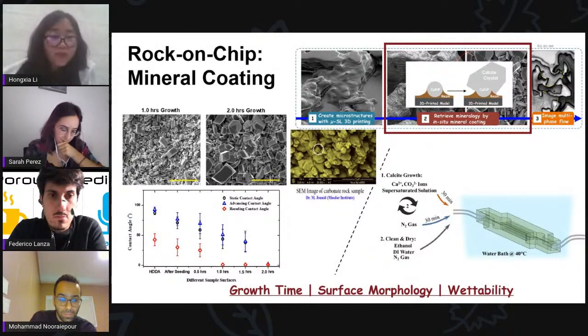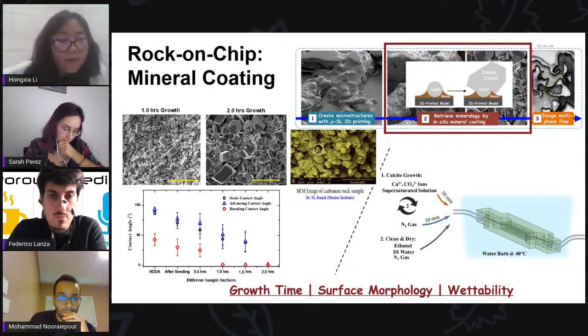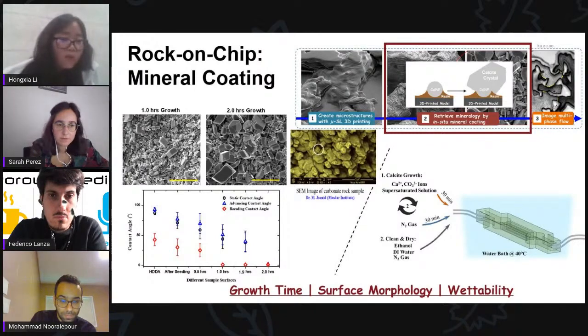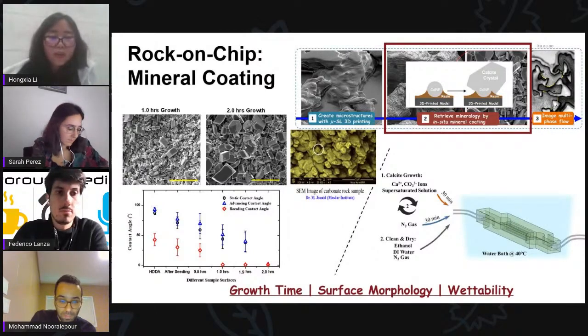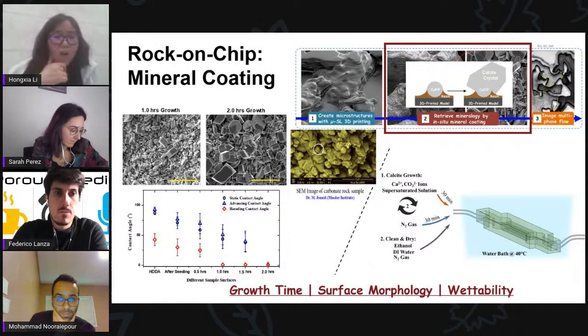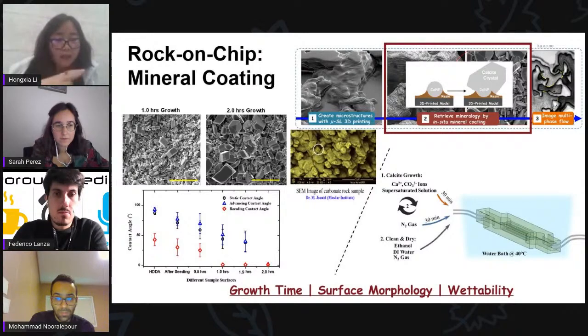Like 1 hour growth gives around 1 or 2 micron, with the scale bar being 5 micrometer, and with 2 hour growth it can go to 5 micron or so. When we stop depends on which type of rock surface or morphology we want to mimic. So this is a real rock surface, and we can see its crystal size. In our community, I believe the surface wettability is always very important in studying multiphase flow. That is also one of our purposes for growing the calcite crystal here, because we can mimic the surface wettability of the natural rock.